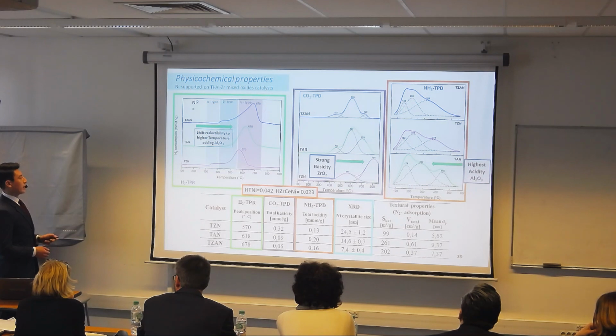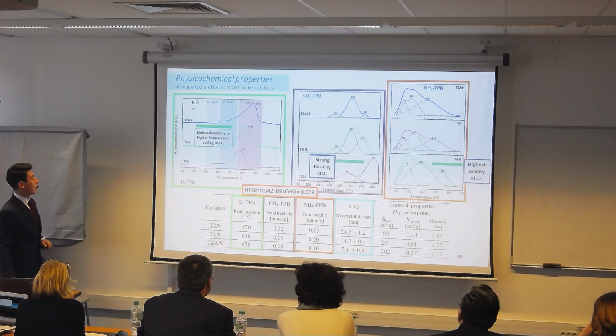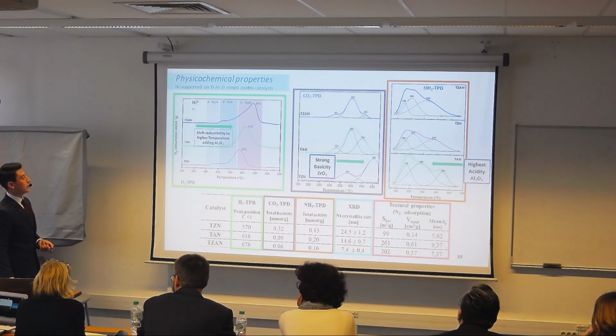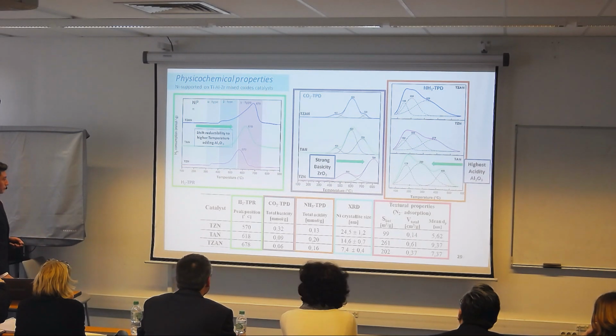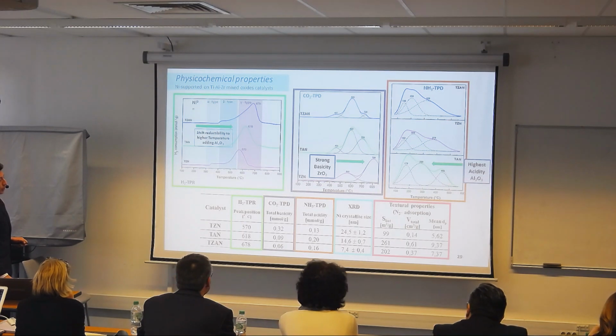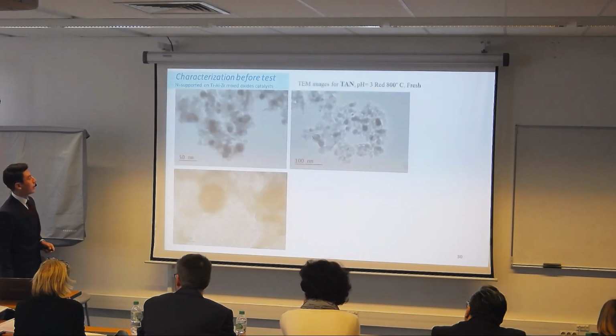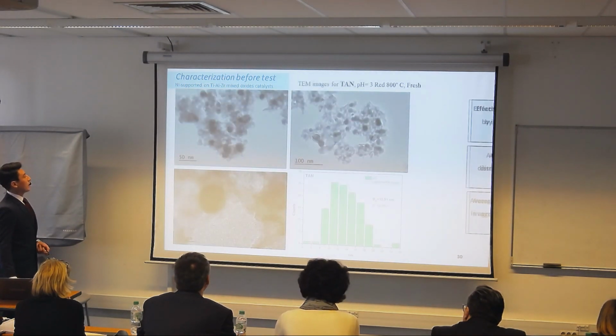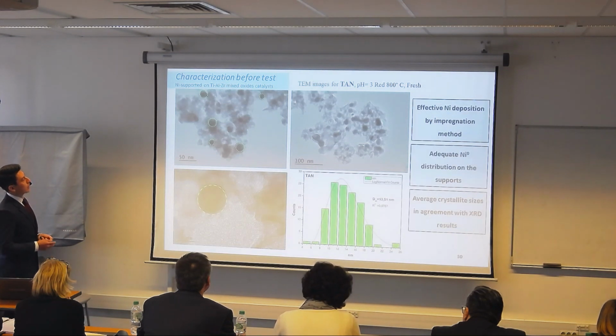You can see here that the values from the previous nickel hydroxide derived catalyst are very low, so we are now having a much higher acidity in our oxides, mainly when we are working with alumina. The alumina is also enhancing the surface area. After the synthesis, we wanted to see what is happening with the distribution of the nickel.